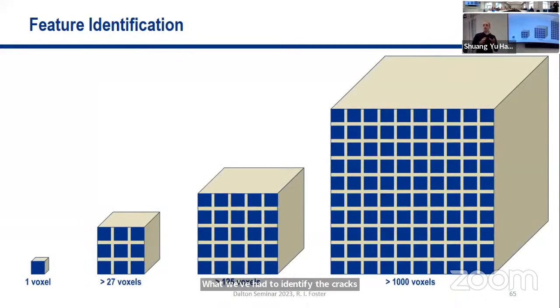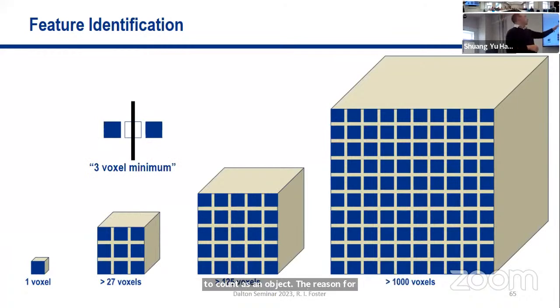One of the problems, however, is what is a feature? So when we're looking at CT and you're looking at voxels and pixels, you could argue, well, if I've got a single pixel, is that a feature? But the problem here is that that could be noise, that could be interpreted in different ways. So often people say, okay, you need to have 3 times your number of pixels to count as an object. The reason for this is if you've got a single feature in the middle, you need at least a minimum of 3 pixels being pixel on, pixel off, pixel on to say that there's an item there.